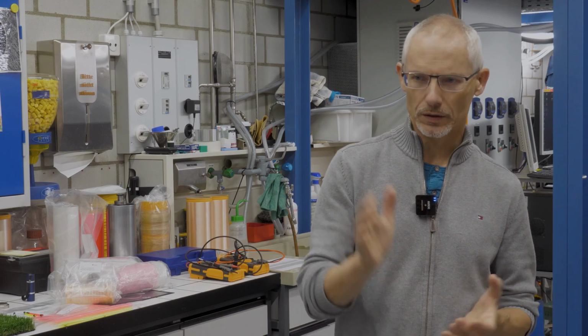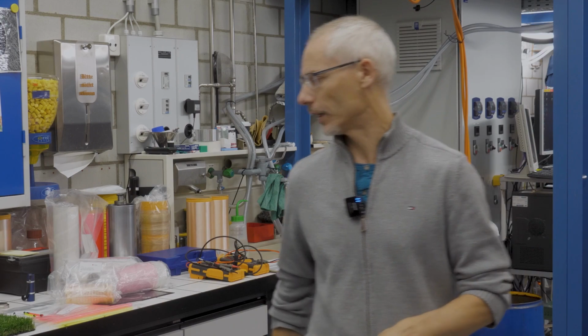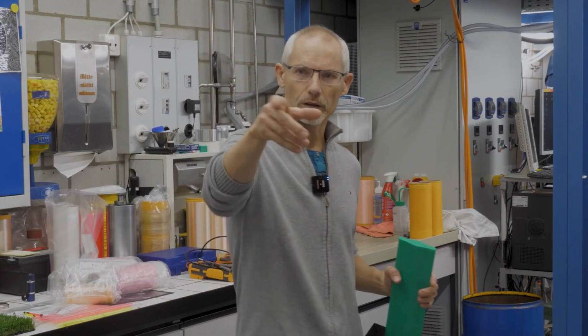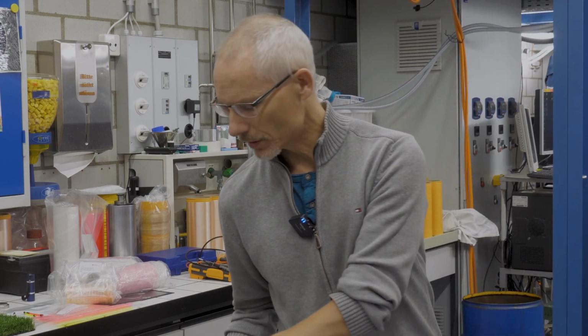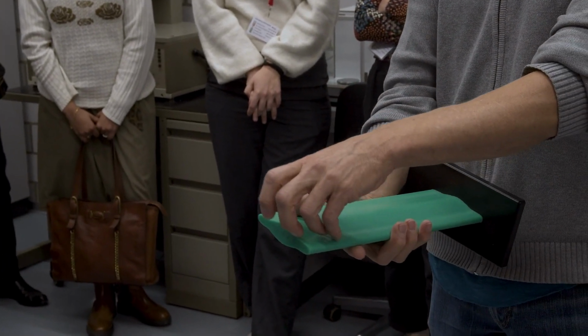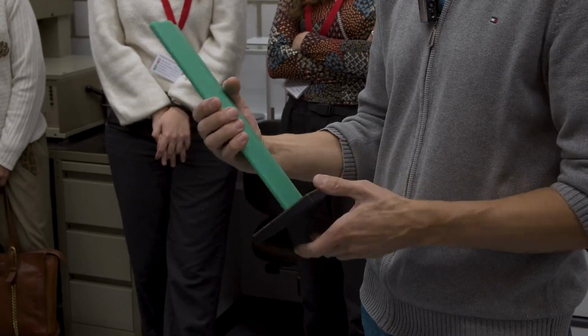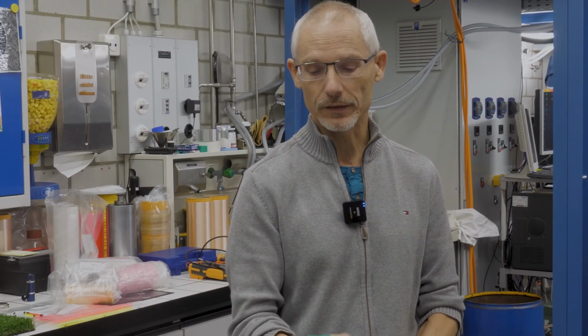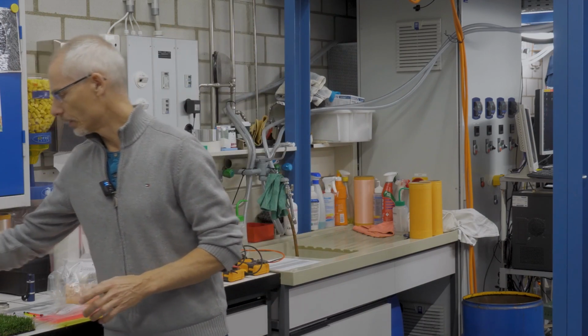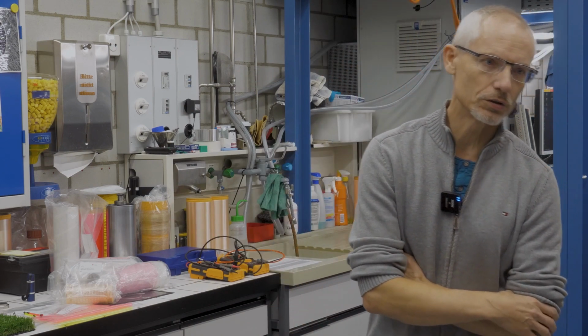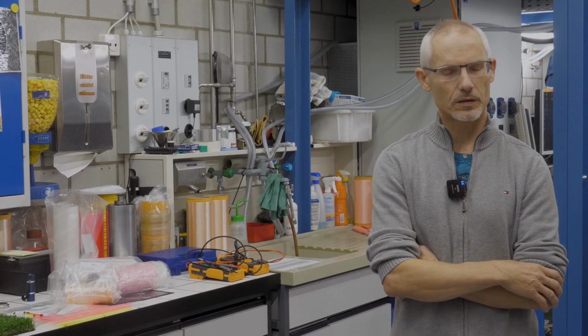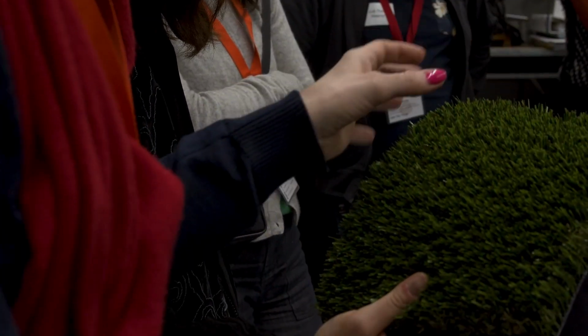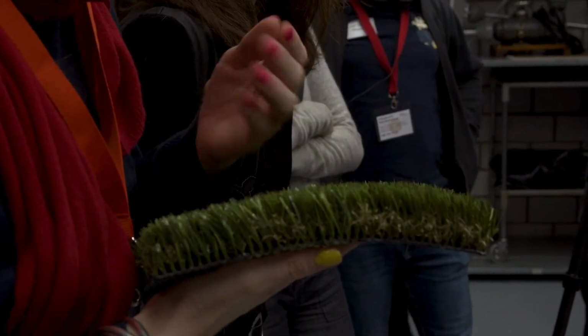That's why with the company I talked about, we started a project where we wanted to combine the two properties of polyamide and polyethylene in one fiber. And actually then you would take a microscope and look at these filaments, how they look like. They have such a cross-section. Meaning we have several cores of polyamide, which give the resilience, so the ability to stand up after having been bent. And we have the sheath out of polyethylene, which gives the skin friendliness. With that, we could solve the problem, and this turf actually works without infill of granules or sand or anything. This is actually in use and sells quite well since more than 10 years. So a very successful project we did together with this industry partner.